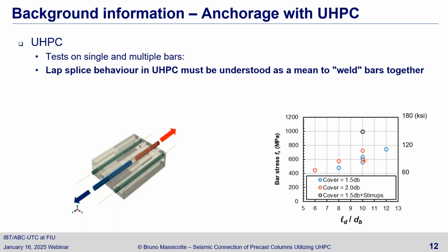So it's very efficient, and this is for conventional commercial concrete. It's not on the upper high side of this material. So lap splice behavior in UHPC, the way it must be understood, it's welding the bars. If you put 2 bars lap in UHPC, they're welded together. That's the way to see it.